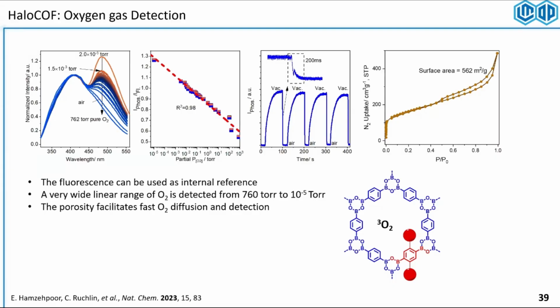Of course, they were highly porous as well. Some were close to 500 meters squared per gram for these doped COFs. And we had both the fluorescence and the phosphorescence co-present. So we could use fluorescence as an internal standard, since it doesn't change with the amount of oxygen, while phosphorescence was changing with the oxygen level. We could track this and make a plot of oxygen sensing using this covalent organic framework. We were surprised to see an eight-orders-of-magnitude linear correlation, on a logarithmic scale of course, with the oxygen level from 10 to the minus 5 torr all the way to 1,000 torr of partial pressure oxygen.